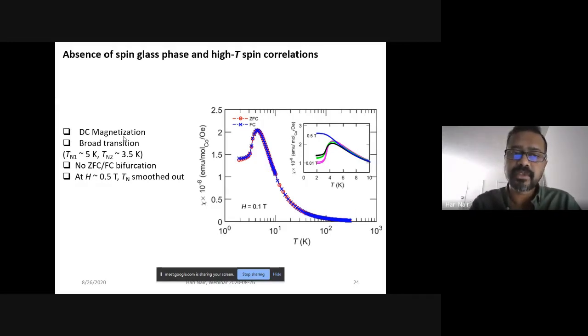If I take a derivative, I see two transition temperatures, which are anomalies in the derivative of chi versus T. One is at 5 Kelvin, another one is at 3.5 Kelvin. So both are at very low temperatures. And if I increase the field, which you can see in the inset, the peak gets smoothed out. That is a classical indication of ferromagnetic correlations, because when you apply the field, the spins align more and more in the same direction, and you get a smoothed out curve where the magnetization is slightly increasing.